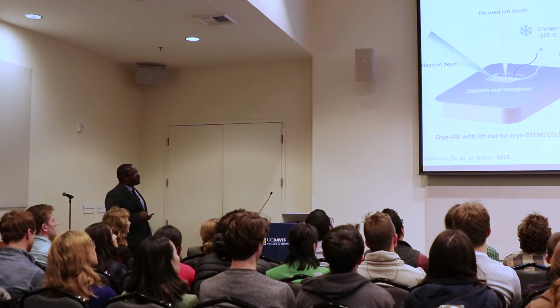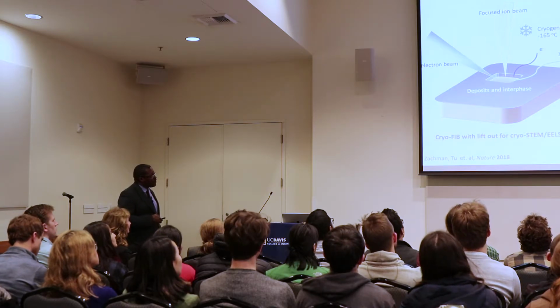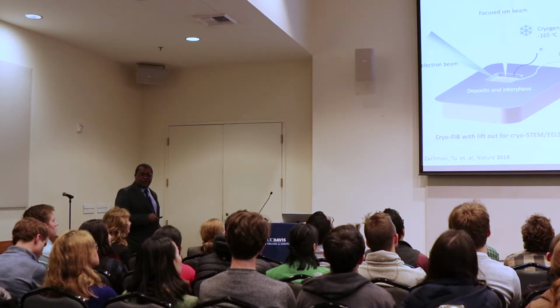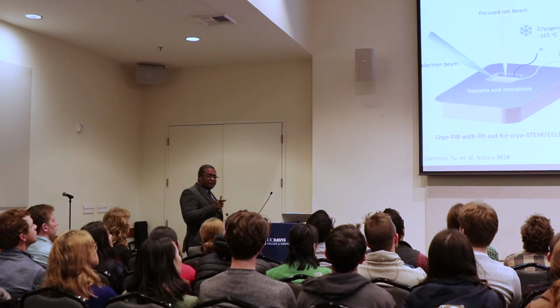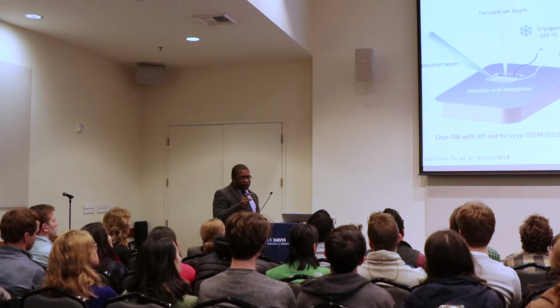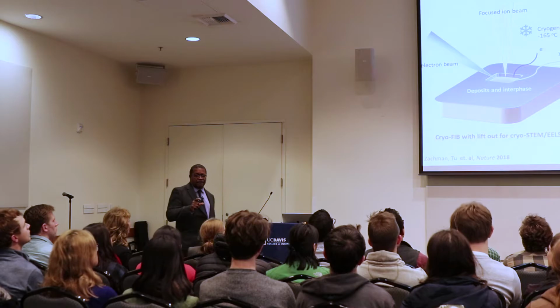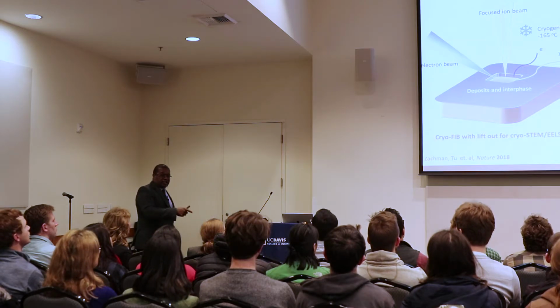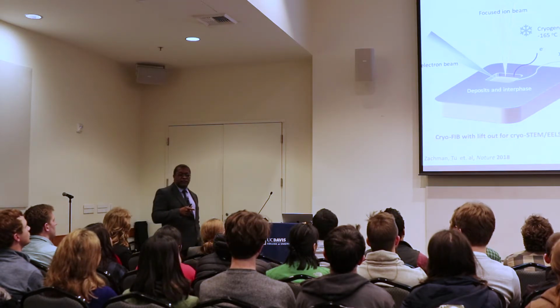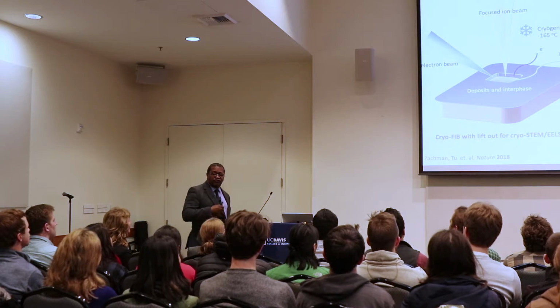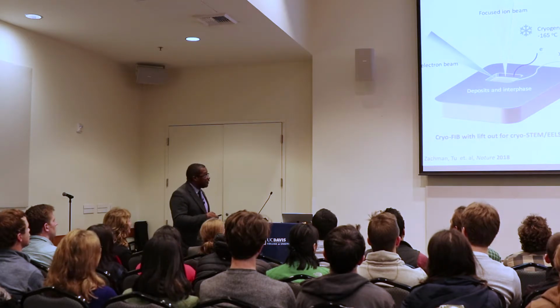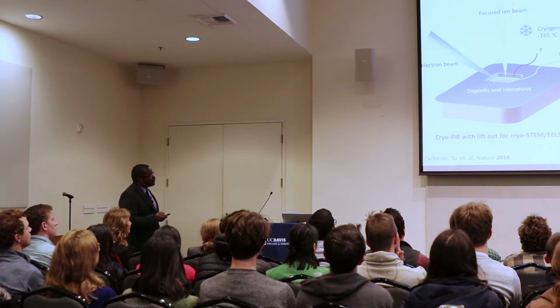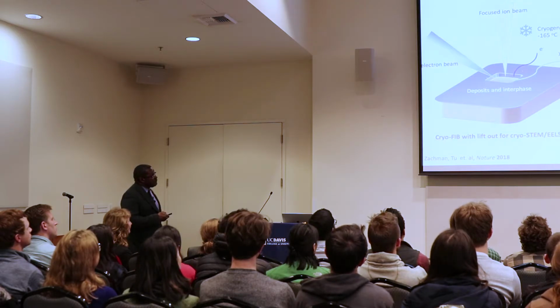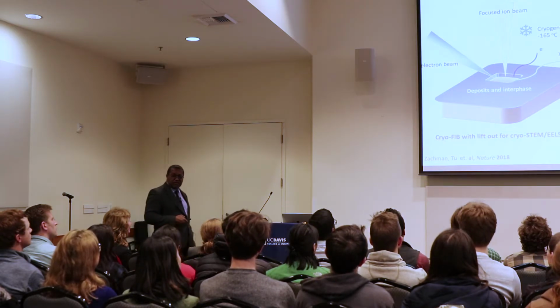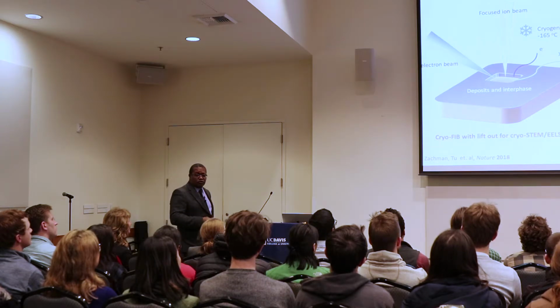So we developed this very clever method called cryofib with lift out, where the idea is that you take the electrode, the lithium electrode, in a battery, either a cycled battery or a stationary battery, and we very quickly plunge it in liquid nitrogen so it becomes really quite cold, and hence you slow down whatever reactions can occur. We take it into the electron microscope, and we use an ion beam to cut out a section of the electrode. We lift it out and turn it on its side.